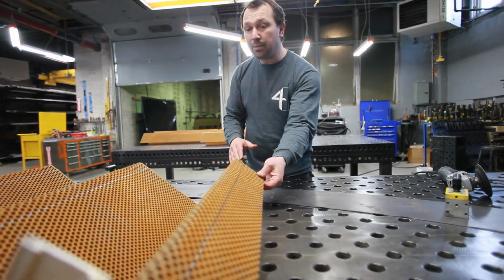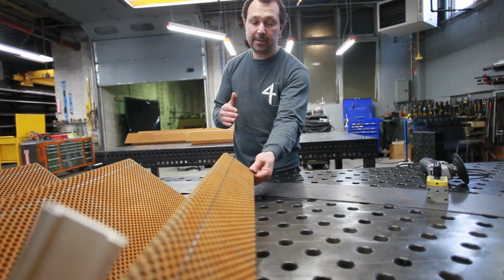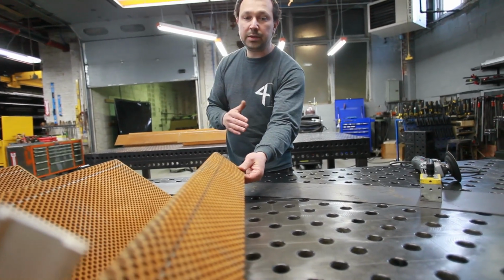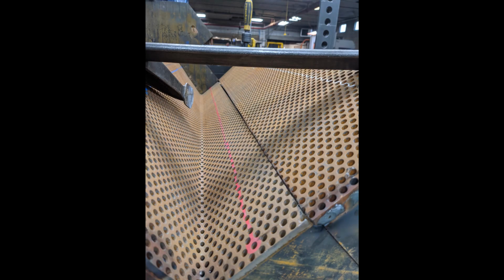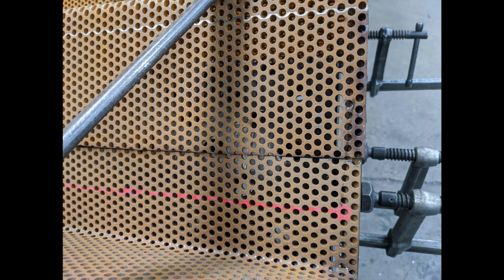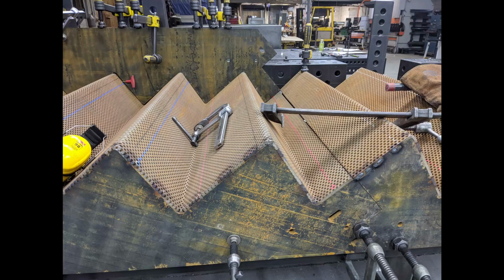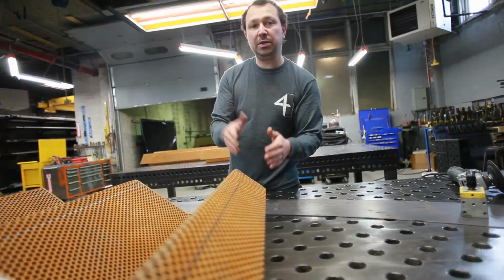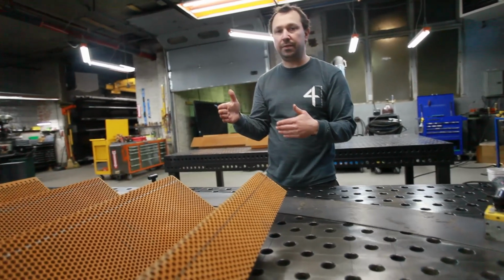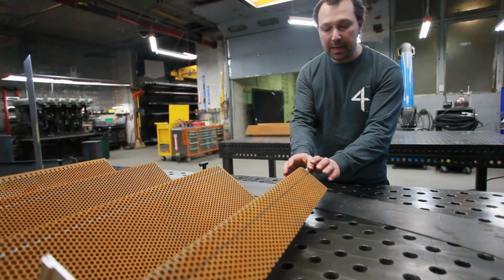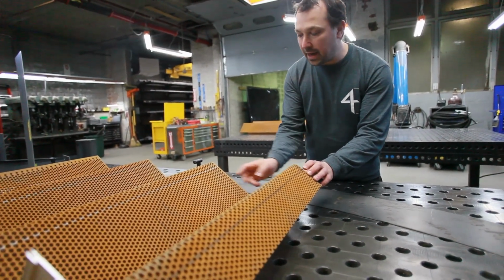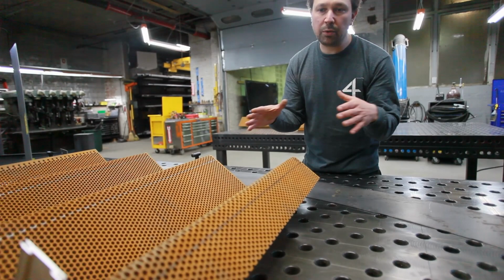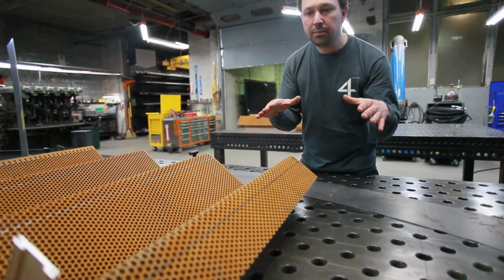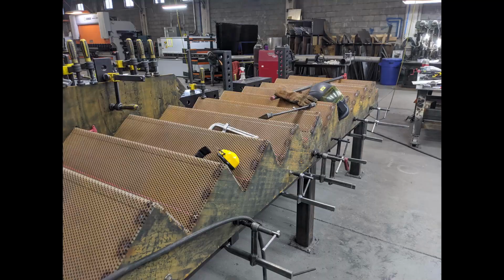Now the big problem of the annealing on flatness for us was that the sheet itself warped, and when we got to some of these junctions, they weren't actually perfectly in line with the pattern, especially the ones that happened sort of in the middle of the sheet. The client wanted to maintain some of the factory edges on this, so we were constrained to where we could place the blank within the sheet.